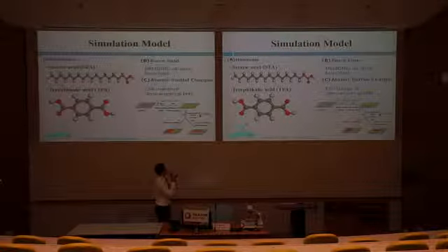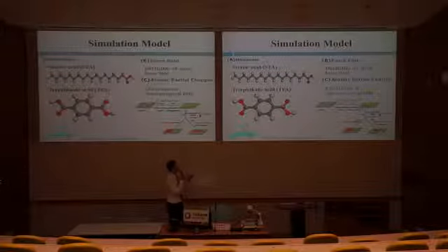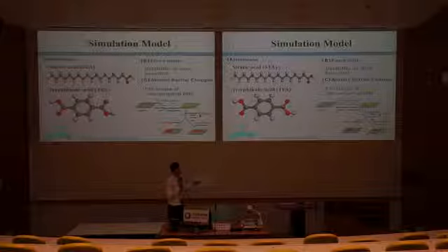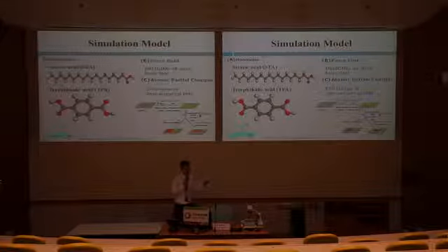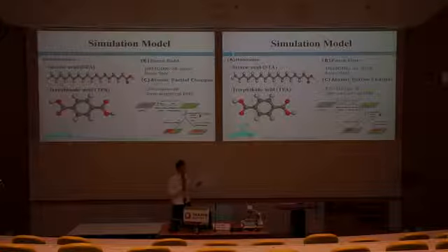We chose stearic acid, which we call STA, and terephthalic acid, which we call TPA, as our examples to construct the 2D supramolecular self-assembly structures. During the simulation, a force field was adopted to simulate the interaction between atoms, and the atomic partial charge was obtained from the electrostatic surface potential charge of a semi-empirical PM6 calculation.